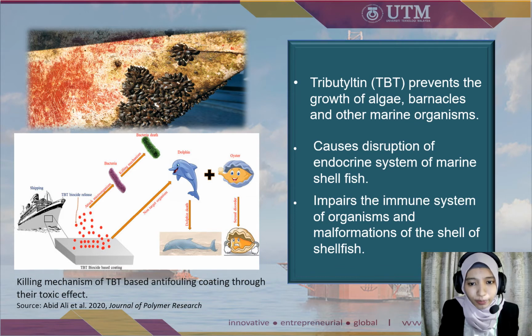causes disruption of the endocrine system of marine shellfish, and it also impairs the immune system of organisms and causes malformations of the shell of the shellfish. For example, here is the killing mechanism of TBT-based antifouling coating through its toxic effects. And also, it was banned by the IMO in 2008 due to these reasons.